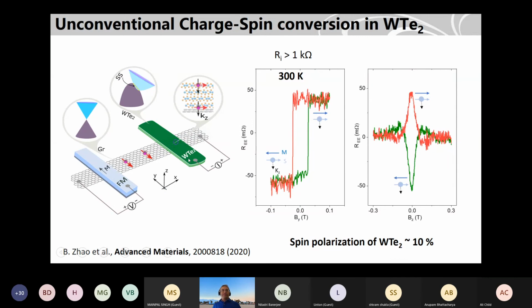What we see here is all at room temperature. If we pass a current in tungsten telluride, it actually creates a spin polarization just like a magnet. You can inject that spin into the graphene, the spin propagates in the graphene, and you detect it with the ferromagnet. These techniques may not be useful for practical applications, but this is quite useful for studying a new material because you cannot do such measurements with other techniques.